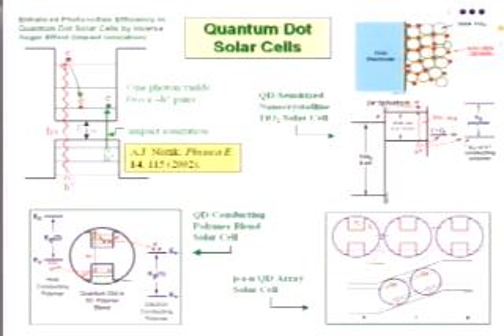I would just mention that there are 3 configurations I could conceive of, maybe there's more, that would utilize quantum dots with this carrier multiplication effect to improve the efficiency. One is just replacing the dye with these multiple exciton generating dots, and then you would get a higher photocurrent. We're going to model the effect in a Grätzel-type cell.